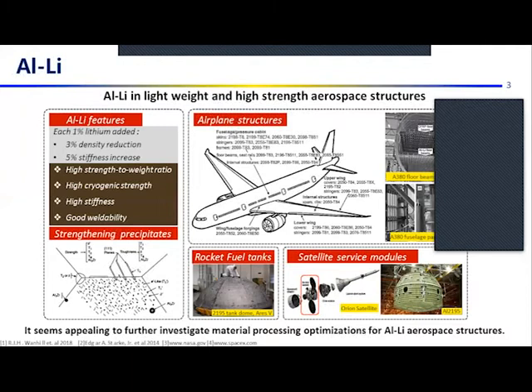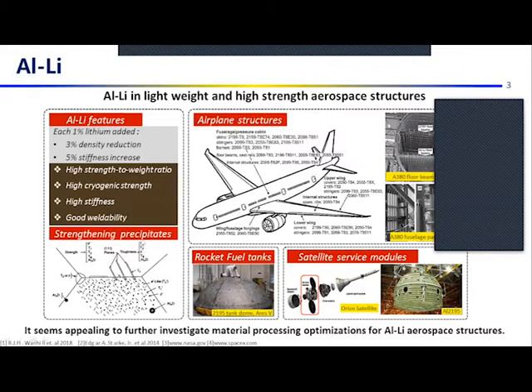Aluminum-lithium alloys have long been a crucial part of the aerospace industry. The addition of lithium to aluminum provides beneficial effects such as high strength-to-weight ratio, high stiffness, and good weldability. The major strengthening effects in these alloys are the secondary precipitate phases, and they have been utilized in aerospace industries such as airplane structures, rocket fuel tanks, and satellite service modules.